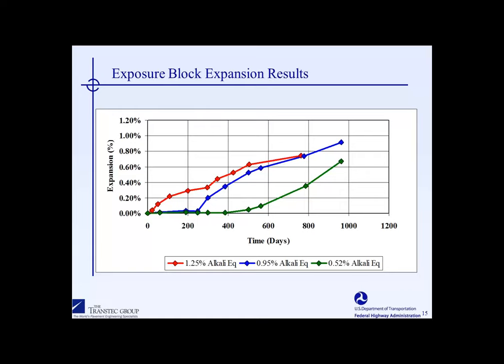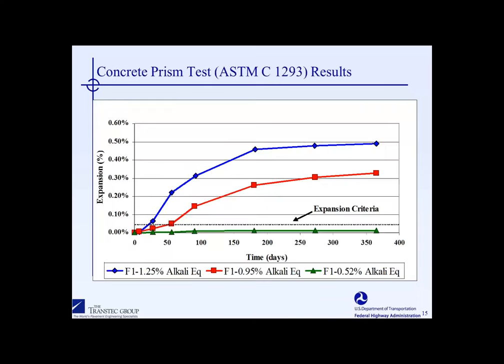Now, what we did with this particular study, and I'm going to show the results next, is we also cast concrete prism specimens from each of these three mixes, and then we tested them following the standard ASTM C1293 exposure condition. And when one looks at the results, you'll see here that the high alkali cement expanded considerably. The next highest alkali content also expanded, and both of them were well above the expansion criteria set forth in ASTM C1293, which is 0.04%.